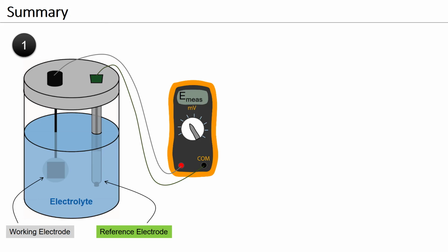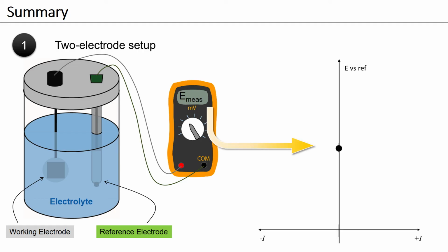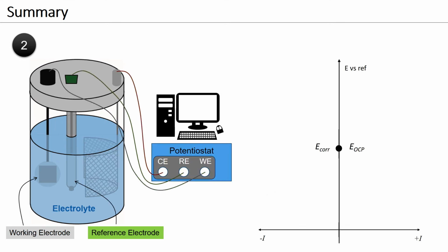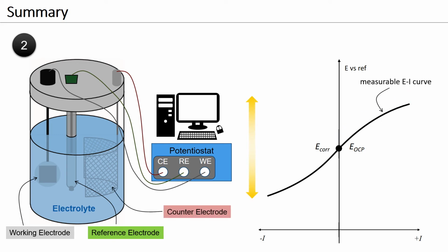In this video, we've seen that the use of a reference electrode in a two-electrode setup allows measuring unpolarized potentials of corroding systems. These potentials are called open circuit potentials or corrosion potentials. To obtain quantitative kinetic information about a corroding system, the working electrode needs to be polarized. For this purpose, a counter-electrode is added. This yields the so-called three-electrode setup that consists of a working electrode, a reference electrode, and a counter-electrode. Ideally, the counter-electrode is placed at a comparatively large distance from the working electrode, while the reference electrode is close to the working electrode.